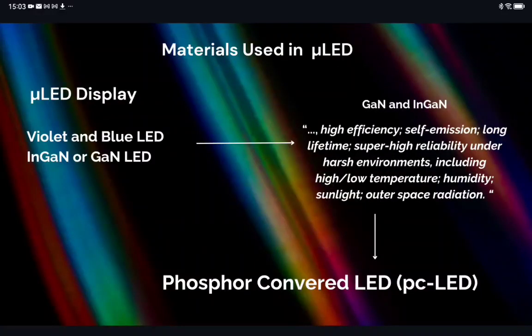So why do we use phosphor-converted LED technology? Gallium nitride and indium gallium nitride are highly efficient photon emitters. It also works in different environments. Indium gallium nitride blue LED reaches external quantum efficiency greater than 80%. External quantum efficiency is the ratio of extracted photons over injected carriers. It represents the ratio between the number of photons and the total charge carriers that recombine together. The high external quantum efficiency makes it feasible to convert the light from indium gallium nitride and gallium nitride using phosphor materials.